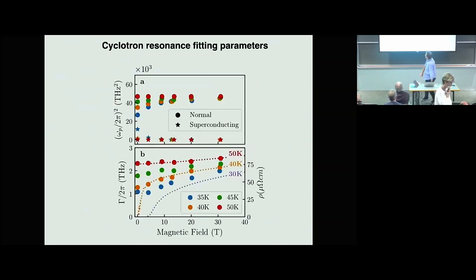There it is. Yeah, so this is, let's say, just for the optimally doped sample that I first showed, the plot of the width of this feature. At the top, actually, it's the plasma frequency from the fit, so it's essentially a measure of this area as a function of magnetic field applied. Blue is a sample which is just barely into the superconducting state. So you get a little bit of funny business at the lowest field on that blue point right there. But then we kill superconductivity right there. And then the plasma frequency, which is here just basically the area of this, is just flat.